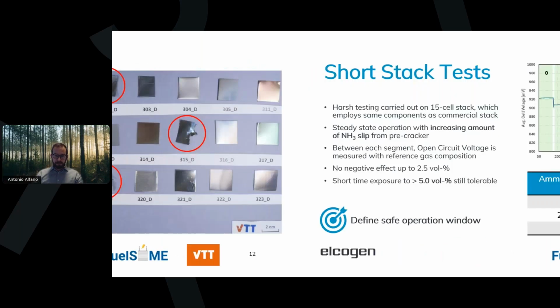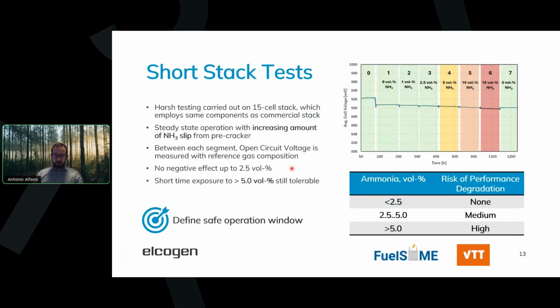The next step from there is restarting short stack testing. So a 15 layer stack, and then we started feeding increasing amounts of ammonia. One of the peculiarities of our stack platform is that the proprietary cell technology enables working at a very low temperature. The stack is effective at already 600 degrees C. So we're feeding ammonia at a relatively low temperature compared to many other solid oxide fuel cell stacks.